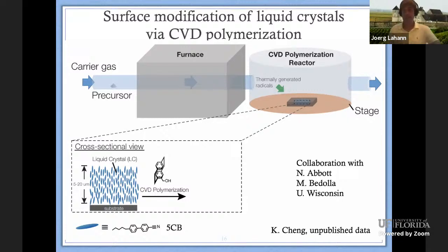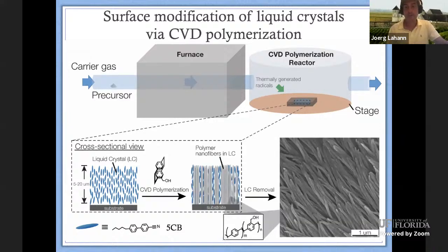Okay, no problem, we'll try that. Unfortunately, the data were very inconsistent. And so when we started to look into this a little bit more, in particular, Kenneth Cheng, a graduate student from the material science department here in Florida, started to look into that a little bit more in detail. And what he found is, well, actually, it's looking very different. So rather than getting a film on top of the LC, the monomers are actually diffusing into the polymer, starting to polymerize on the bottom, and then basically are being templated into nanofibers.